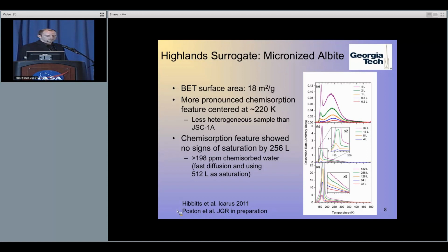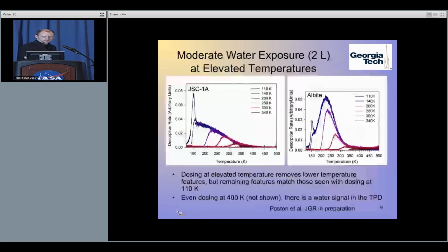So we stopped the experiments at 512 Langmuir, and we just said, well, let's use this value as a lower limit. And that lower limit turns out to be 198 ppm of water, and those ppms are by mass.